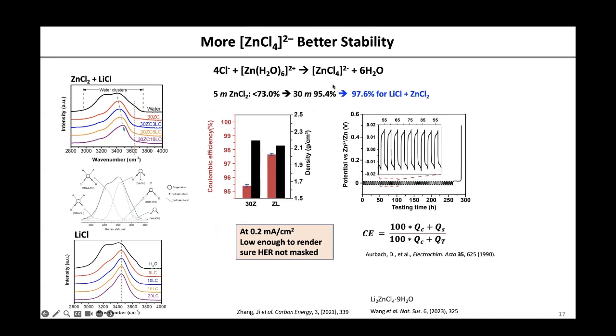By having a concentrated solution, we are producing a higher Coulomb efficiency compared to a low concentration. At 30 molal, you get 95.4%, while for a dilute electrolyte it is only 73%. But now by adding lithium chloride, this Coulomb efficiency is even better, 97.6%. And by the way, we use this reservoir calculation method for calculating the Coulomb efficiency, which was first introduced by Dr. Aurbach. Recently there is a report by Dr. Chunsheng Wang, with a specific ratio between lithium chloride and zinc chloride, and they also observed very high Coulomb efficiency.